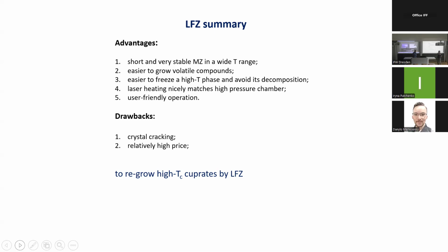Ruthenates, strontium ruthenates, this also works. I mean, there is no big difference, because you could grow this material by conventional image furnaces, but they have been grown. But Andrei said that Bisco is possible, and it would be nice for Ira to come and start to try. But as far as I understand, the main problem of Bisco is the low melting temperature. Which temperature is for Bisco? Around 900, even lower. But YBCO 1020, 1030.